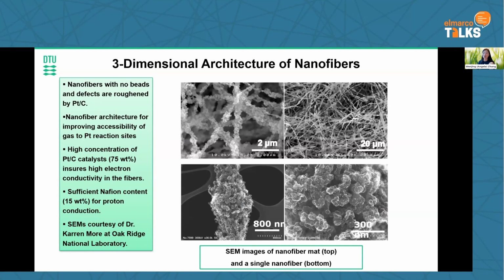And each fiber is roughened by the catalyst. This is a platinum carbon catalyst. With this kind of design, we can reach a 40% reduction in platinum consumption with even higher performance than the conventional ones. So with this, we actually opened the entire field of electrospinning for energy devices, especially for electrochemical